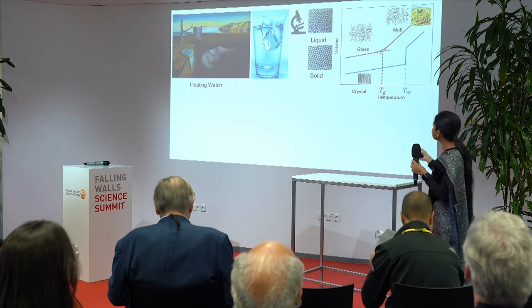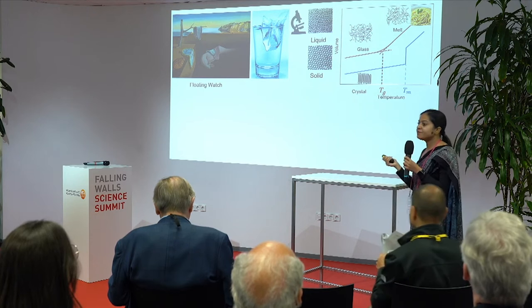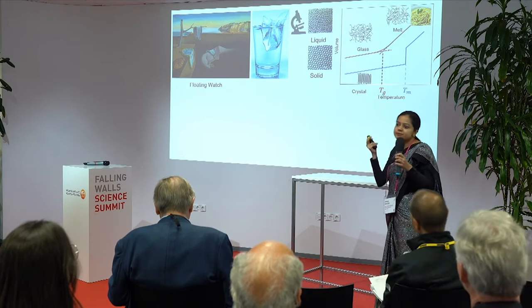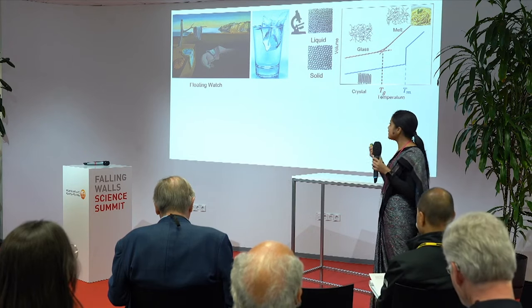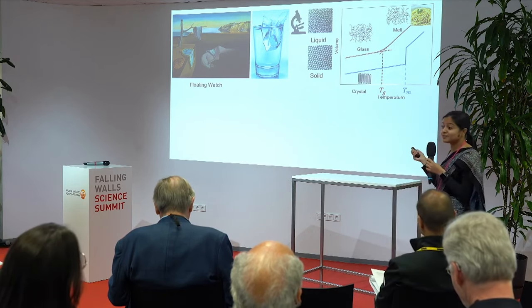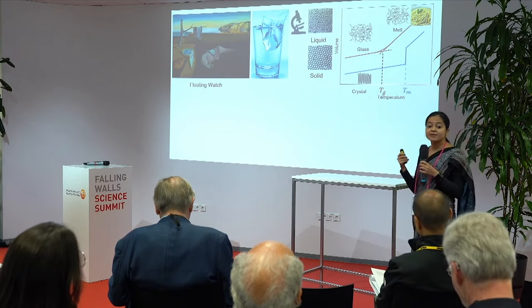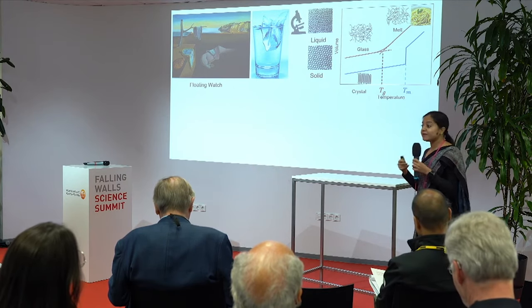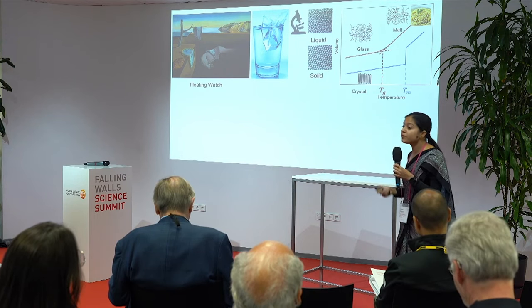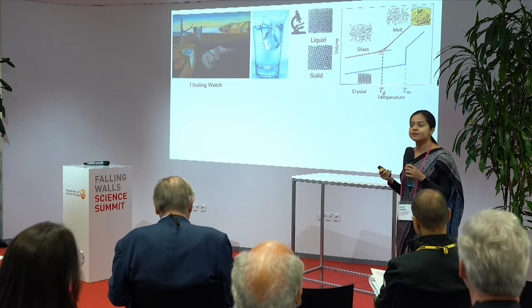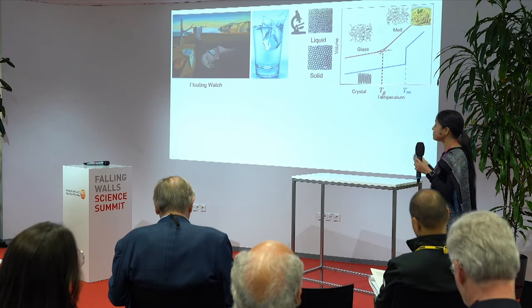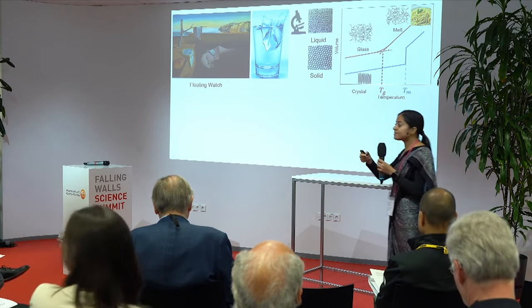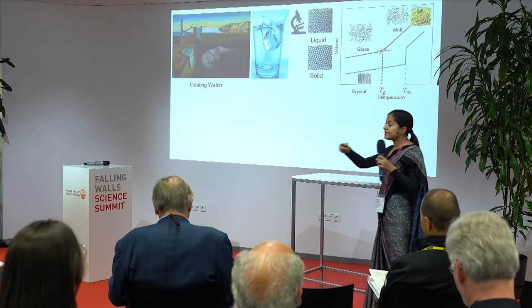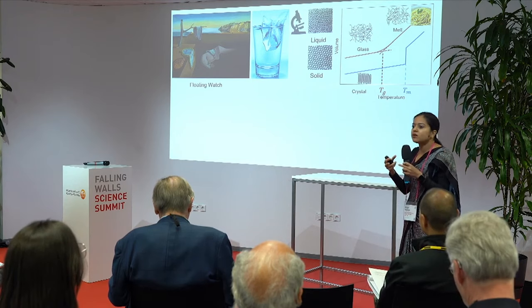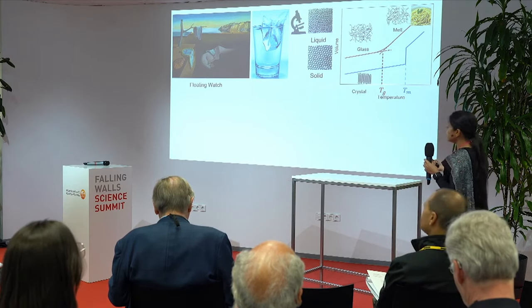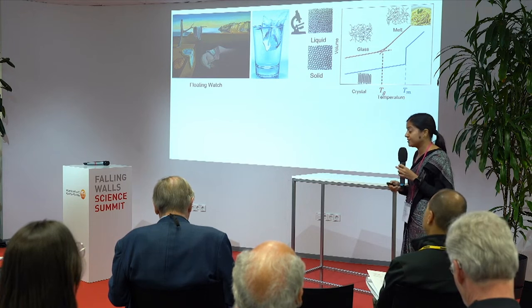And since the structure of the melt and the glass are pretty much the same, from the statistical physics point of view it's a problem, because there is no stark difference in structure, whereas the dynamical or mechanical properties change a lot. And from an engineering perspective, for each polymeric material that we use in daily life, we need to know the glass transition temperature precisely. That's because above the glass transition temperature the polymer is rubbery, whereas below it, it's like rock solid. So we need to know the glass transition temperature for each polymeric material.